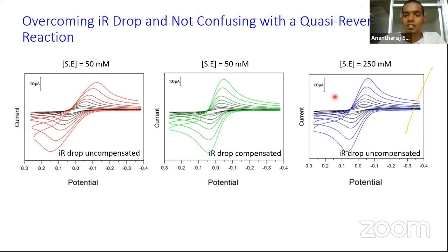So in this case, this reaction is actually reversible, but we see peak shift with increasing scan rate because of ohmic drop, the IR drop, the solution resistance. So this is how you can distinguish between the actual quasi-reversible reaction and the reversible reaction that is affected by IR drop. So this is one example of how voltammetry can be effectively used in order to distinguish between the type of reaction.